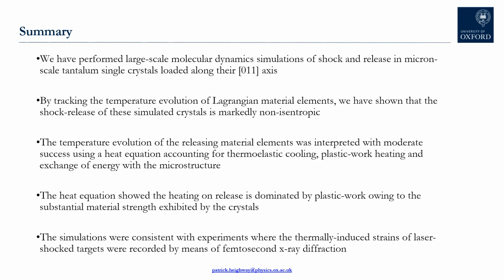So these results show that the assumption of isentropic release that features in many textbooks on shock physics should be treated with caution, particularly if one is dealing with micron scale targets for which the strain rate in the release fan is extremely high. These elevated temperatures assumed by such targets during release necessarily alter its trajectory through phase space, and thus where it might encounter any phase boundaries during unloading, and surely also influences the kinetics of any transitions or reactions that might ensue during release.